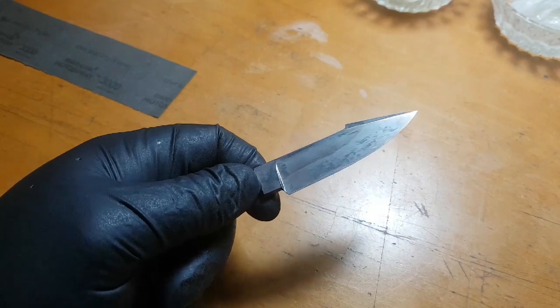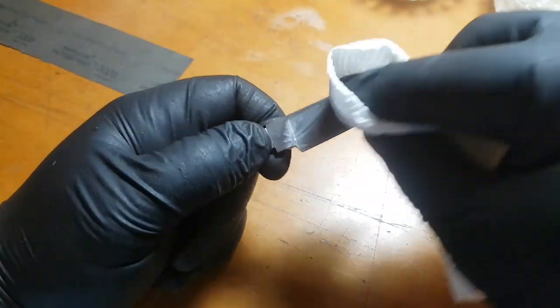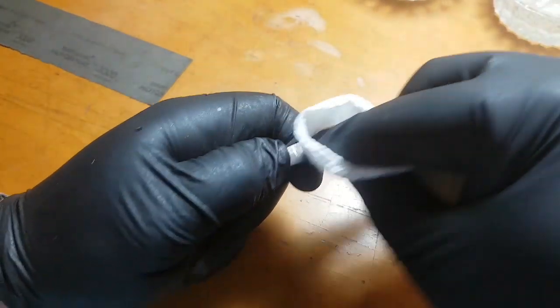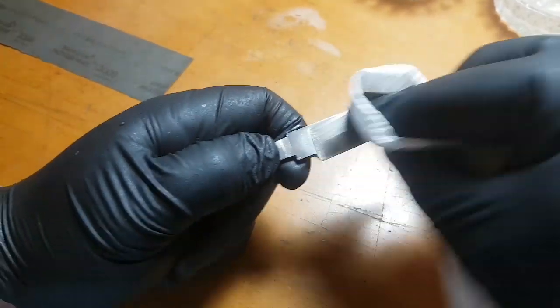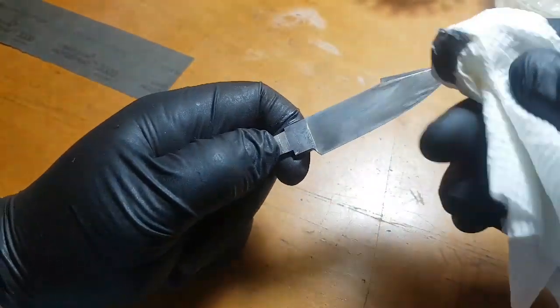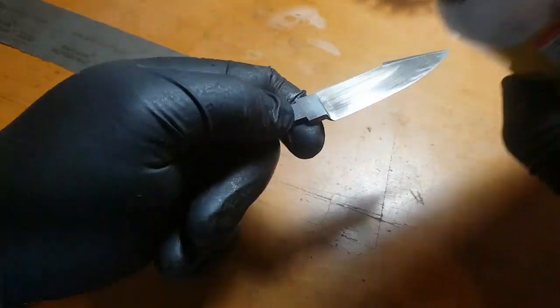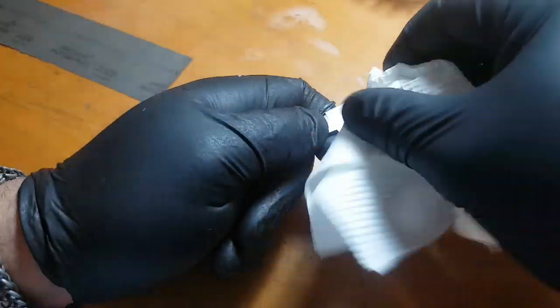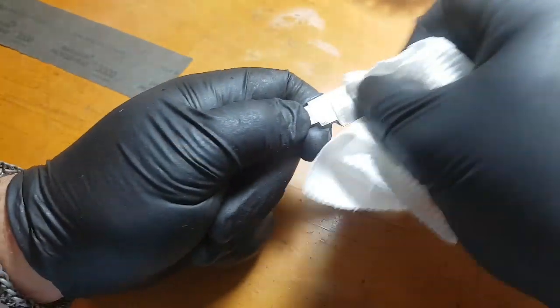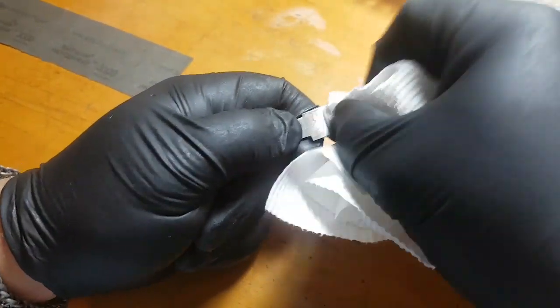So you can see here that it's a little bit darker than it was the last time I polished. And I won't entirely chase out all of these oxides in this polishing step. I'll only do that in the last one. And I tend to do normally 3 cycles, sometimes 4, until I'm really happy with how the Hamon looks and if I'm getting that activity that I want.